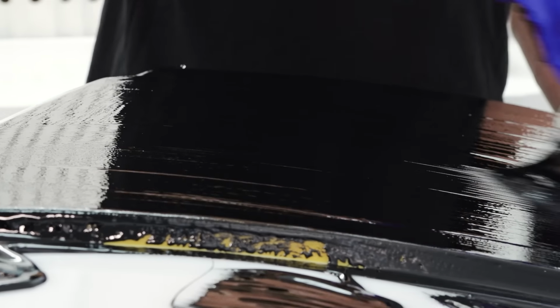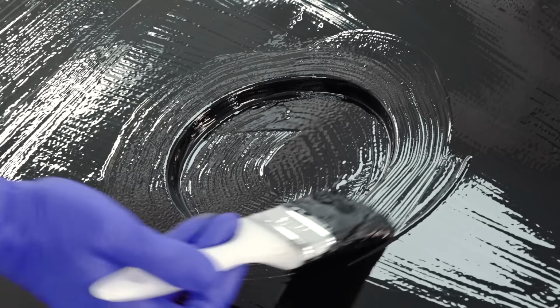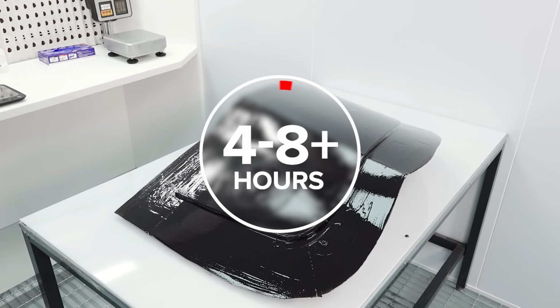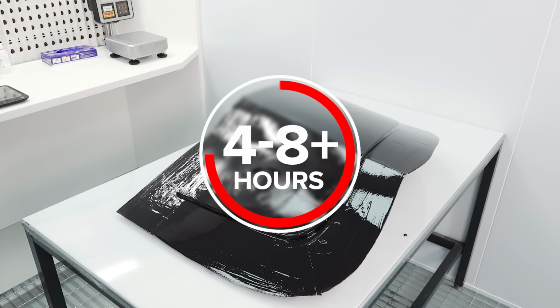If you were to leave areas pooled up like this, then there is a strong risk of the gel coat excessively shrinking while it cures, which can lead to pre-release and areas of distortion. Once you're happy that the coat is even, it can be left to cure for 4 to 8 hours.